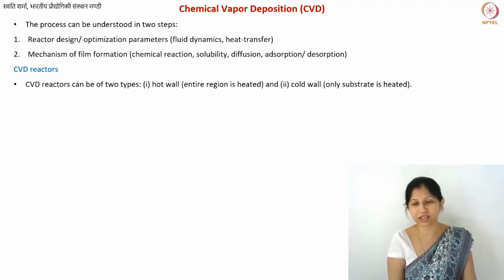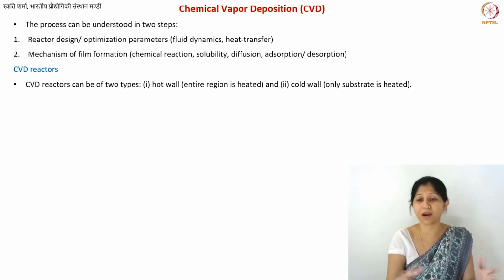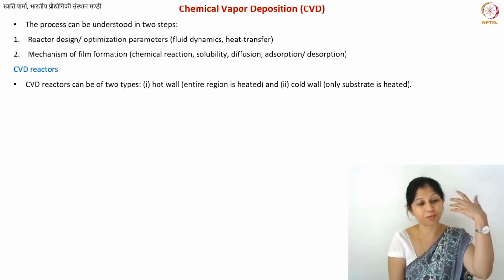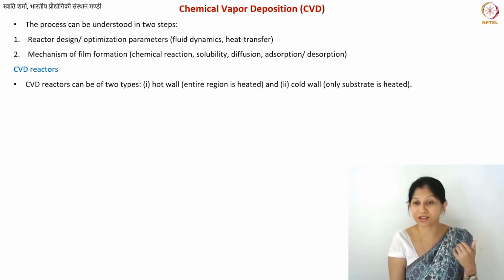In fact, just by changing the catalyst, you can get a different carbon nanomaterial altogether. What does that mean? That means that the catalyst or your solid support does have a strong influence on the process. So there is something to do with the deposition of metal, and then the solubility of that metal, and then the precipitation of that carbon structure. Definitely there is something there, and this mechanism is still being investigated.